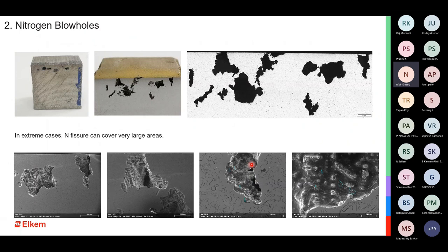The second part, another interesting part of it, is the nitrogen blowhole. This is not something which will be as smooth and rounded as other gas defects. You'll have more of a fissure kind of defect, and this can be very severe. It could be present in the entire part of the casting, or it could be present in a small area. That again depends on the type of casting design, the solidification behavior of the casting, and of course the percentage of nitrogen present in your system.